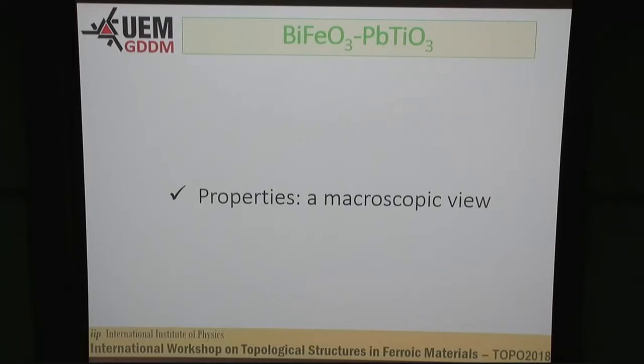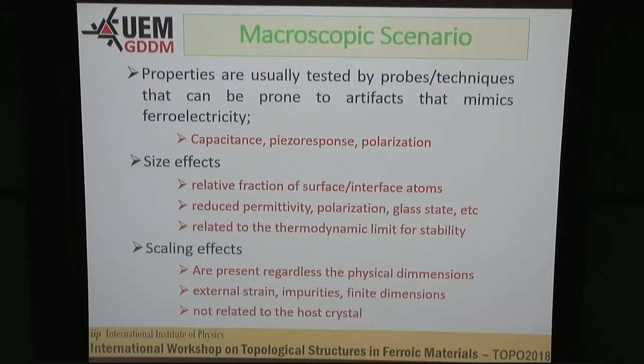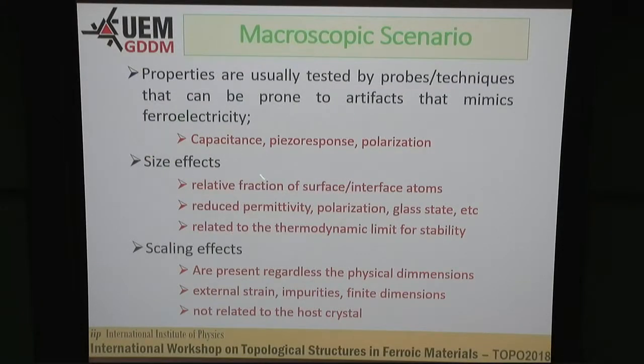Okay, we did a lot of characterizations to see how is the microscopic response of these materials. When you do some characterizations to see the response of these materials, you have some problems, or not problems, but effects that are very difficult to separate from your main results. For example, properties tested by probes or techniques that come from artifacts that mimic ferroelectricity, like capacitance, response, polarization. We usually have size effects, relative fraction of surface and interface atoms, and other problems that are related with the size of the polycrystal. And also scaling effects that are there regardless of the physical dimensions, like external strains, impurities, finite dimensions, and so on.